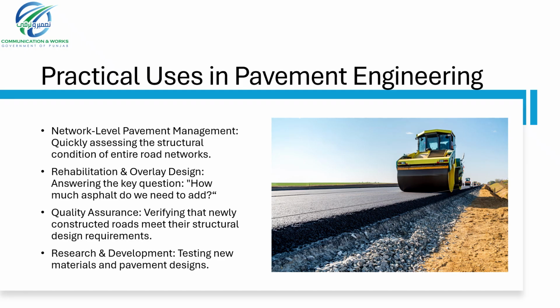The FFWD allows us to evaluate the in situ elastic moduli, or stiffness, of all structural layers in an existing pavement. This information is fundamental for assessing the current structural capacity of the road network. It is also integral to rehabilitation and overlay design. The calculated layer moduli are used in software programs like ELMOD to determine a pavement's remaining service life and to execute the structural design of necessary overlays.